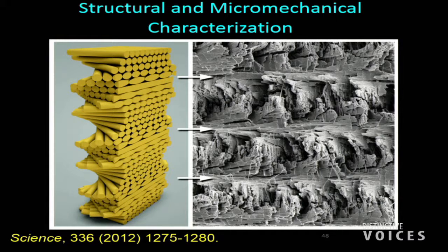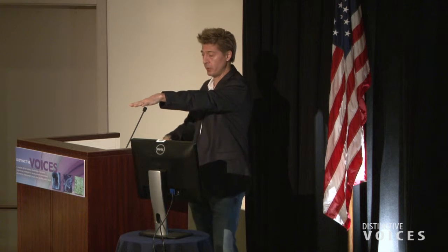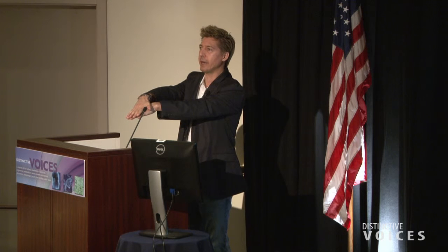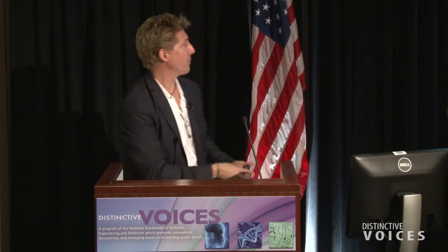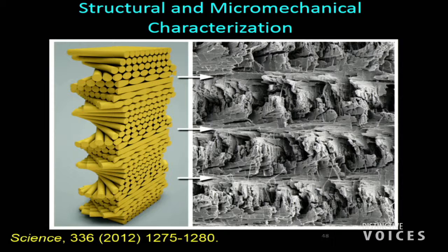All a helicoid is, and the schematic shows it very well, is you've got unidirectional fibers that are oriented, let's say, at 0 degrees. The next layer that's stacked on top of it is stacked at some small angle, let's say 2 or 3 degrees. Then there's another at 6 degrees and 9 degrees, etc., until there's a complete 180-degree rotation of these fibers. And then it will repeat itself over and over again. So why is this structure so important? What does it do for toughening the club?